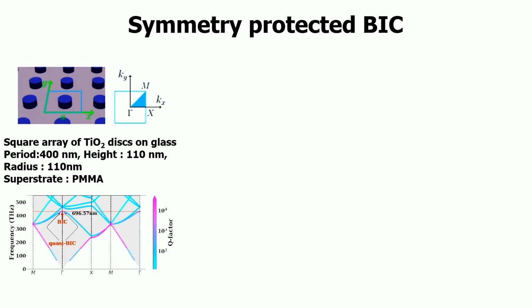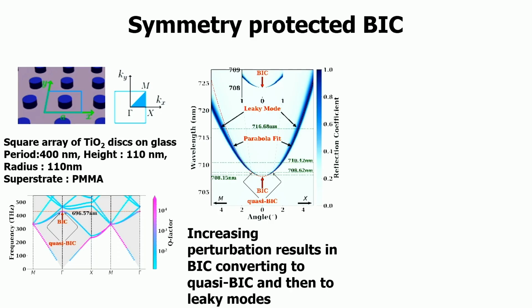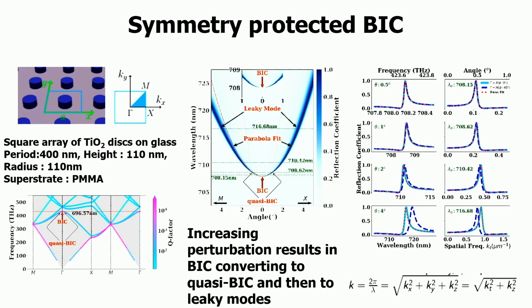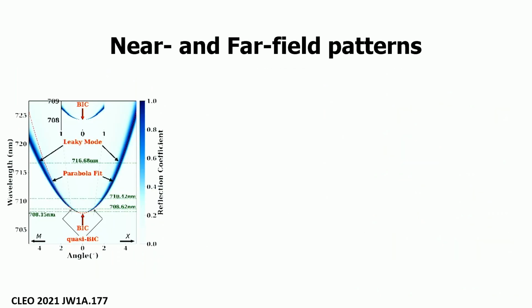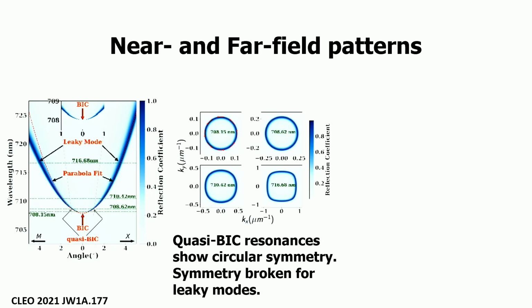So here basically there's one lattice of TiO2 disks on top of glass, and so this is symmetry-protected, so you have the BIC, and if you go away from the BIC, you go to leaky modes eventually. So these quasi-BIC modes are finite line width modes, which are very close to the BIC on either side. So these have interesting properties like asymmetric line shapes, etc. To identify whether a resonance is BIC or not, you can look at the far field reflection.